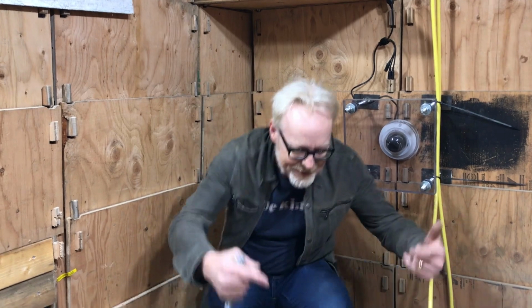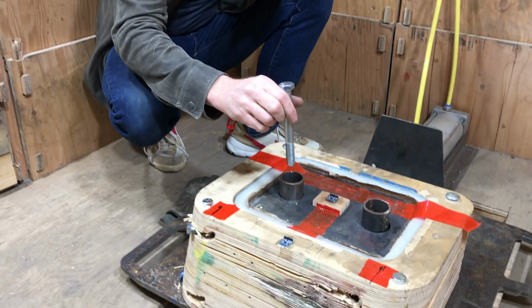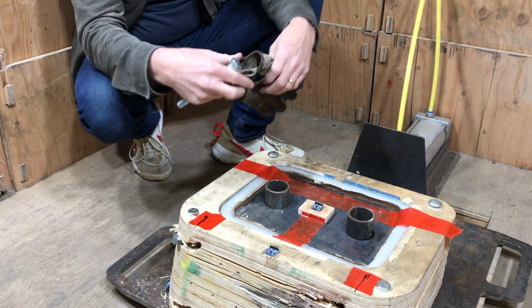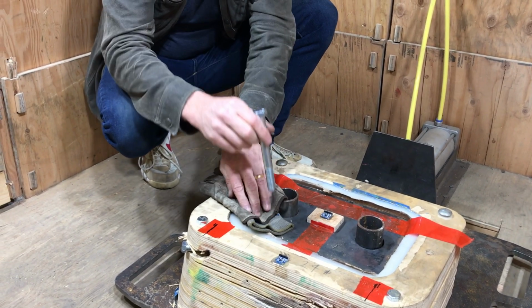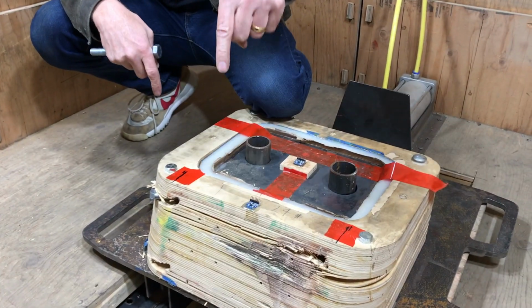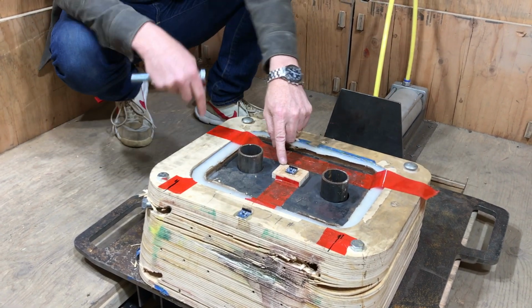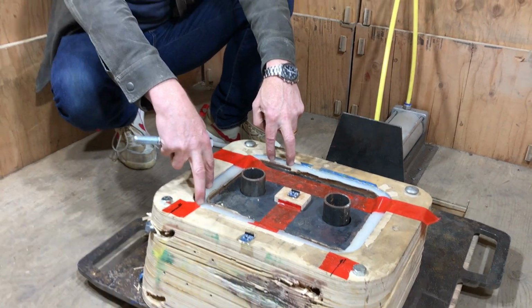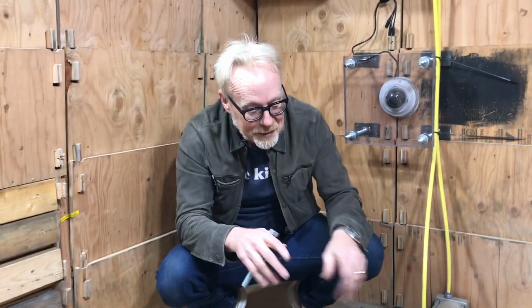And the way to think about it is the impact of a hard thing into a hard thing creates a very, very powerful force in a very short period of time. And you can kind of hear it if I do that. You can hear how sharp that sound is. But if I give a little bit of strain relief to that sound, a little bit of padding, you can hear, right? One graph you can picture as a sharp point and the other has a little bit of a flat plateau on top. Well, that is why this accelerometer mounted hard to the buck often is exceeded and doesn't give a reading, whereas this one, buttressed between the Shore 60 hardness buffer here, actually does give a reading. And by cross-correlating that with the rotational forces and stuff, hopefully they'll be able to get a genuine reading on how much force is involved in the impact.